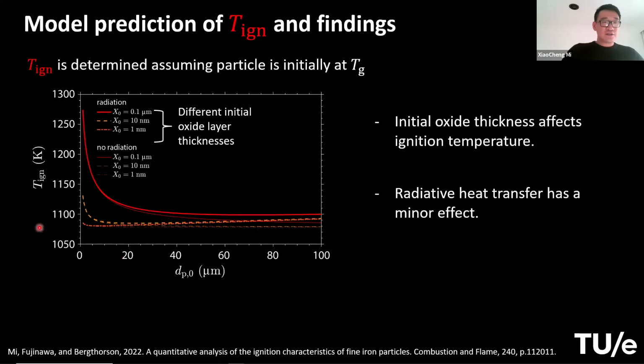And here are some results. This is the ignition temperature as a function of particle size. The different curves show the results for different initial oxide layer thicknesses. You can see that the ignition temperature is highly dependent on the initial oxide thickness. With a relatively large initial thickness, it requires a higher ignition temperature to trigger thermal runaway. Radiative heat transfer to the surroundings doesn't have a very major effect on the ignition temperature.